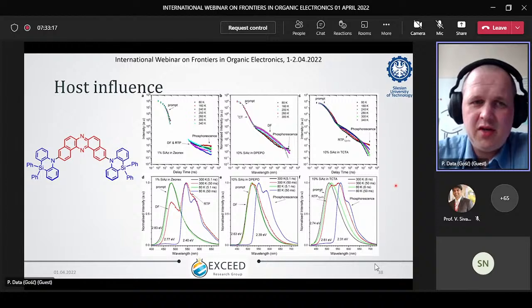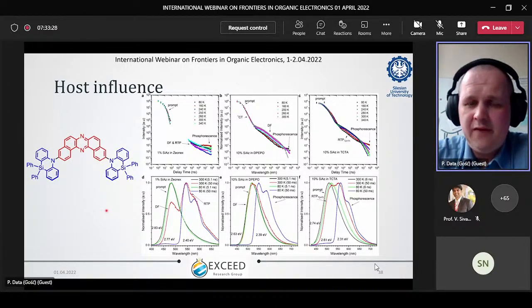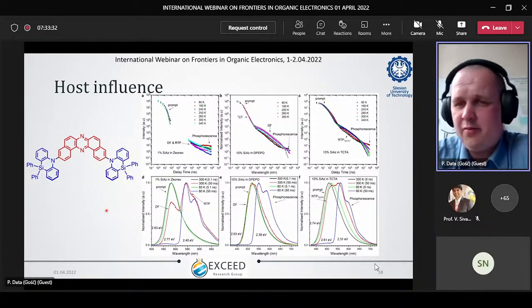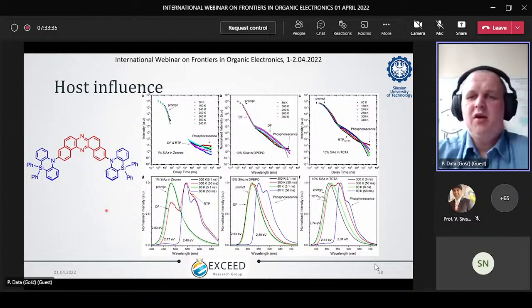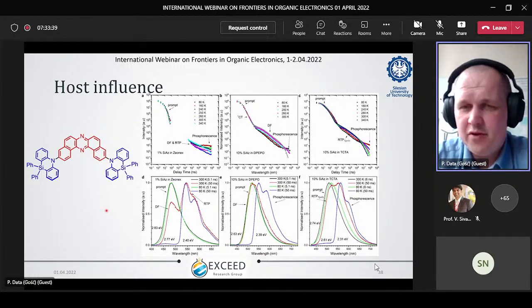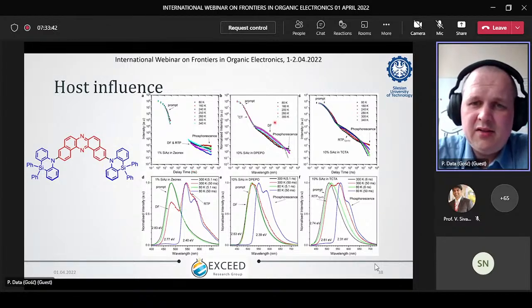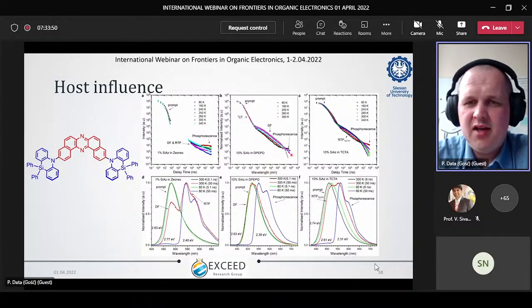When you have your molecules, you can manage this again by the host. So you are not affecting only your charge transfer state, but you can also affect the conformation which is formed by evaporation, because in this case we want to have efficient OLED devices, so we are evaporating our molecules. And here is an example that in the more polar host, we are forming an emitter which is purely TADF, and we have pure equatorial conformation.